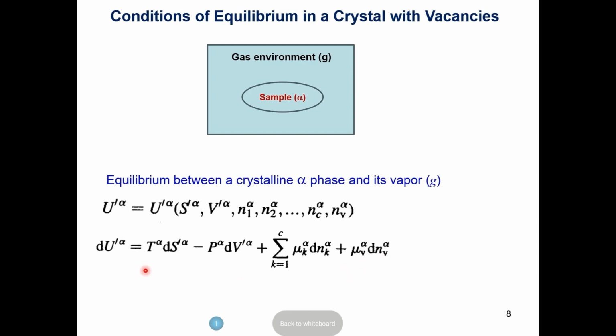Then you can turn around and express this in terms of change in entropy—I'll talk about that next time. So you can rearrange this if you're interested in finding out what is the change in the entropy of your solid that is interacting with the gas phase. Similarly, you can write an equation for the gas phase. So this is for the solid phase—what is happening to your sample versus what is happening to the gas phase. And you will notice that when I write this for the gas phase, I write the chemical potential for the components that are in the solid, and the vacancy term—this is the chemical potential of the vacancy in the solid.